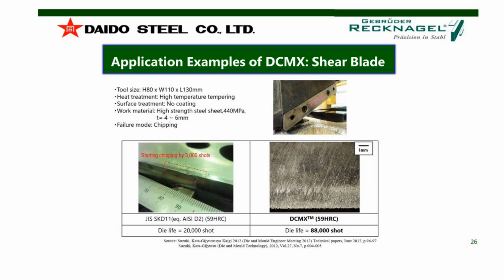A shear blade is also a typical application for DCMX. As you can see in the picture on the left side, the customer had problems with very early chipping after 3,000 shots. The total tool lifetime with D2 was about 20,000 shots. Then he switched to DCMX with the same hardness, and the tool lifetime goes up to 88,000 shots. Also a perfect idea to use DCMX for this shear blade.